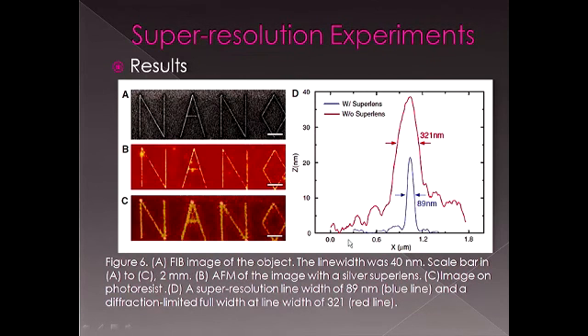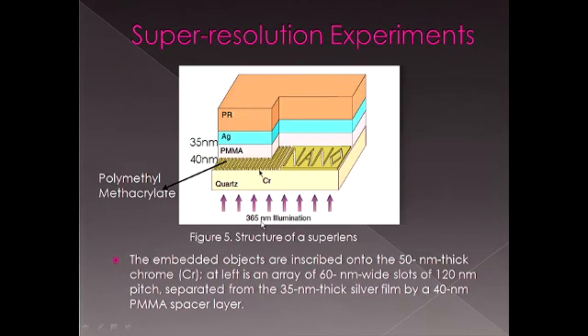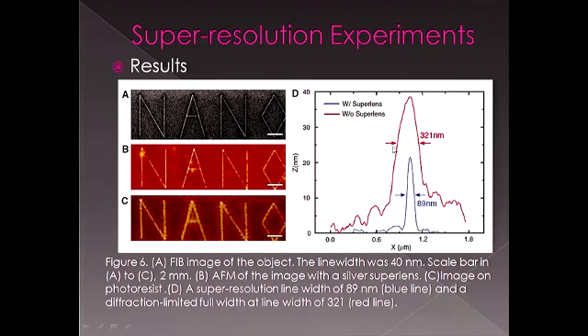So here is the cross section of the photoresist. We can see the line with the red lights for without superlens and blue lights for with the superlens. We can see that without superlens, the line width of the pattern is about 300 nanometers, which is very close to the wavelength they are using. So this line is still limited by diffraction limit.